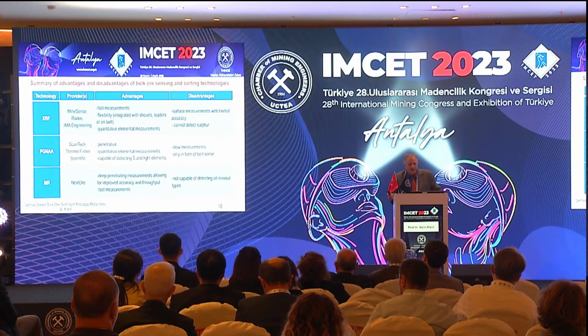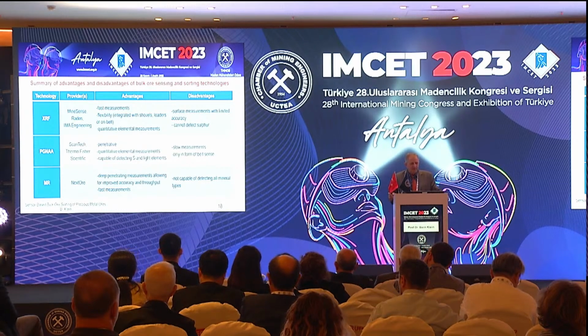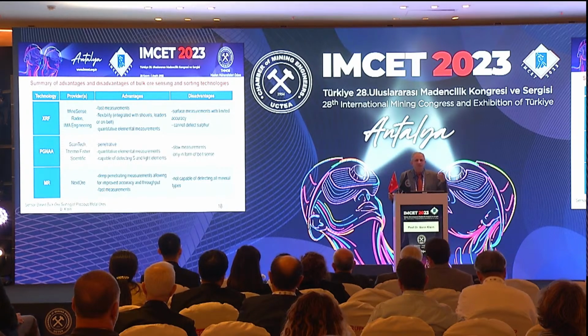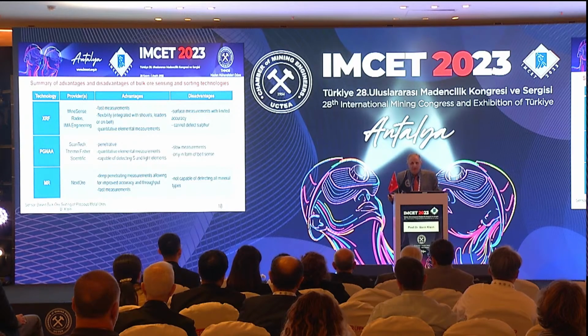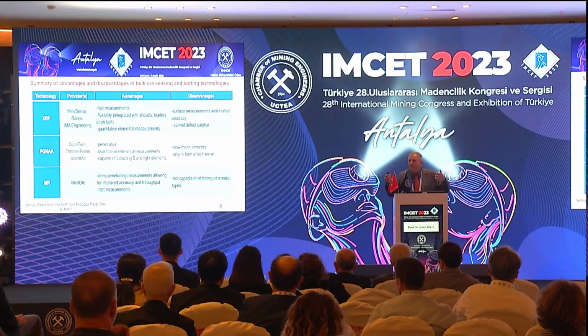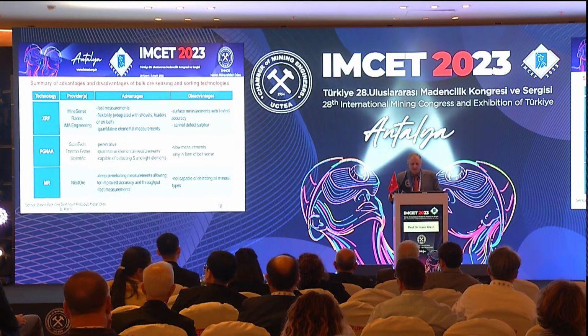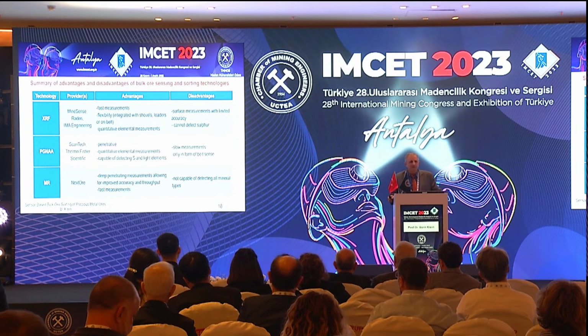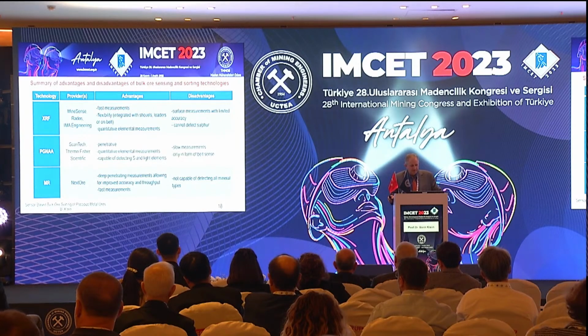The PGNAA can measure a lot more elements than XRF, including sulfur, and it's penetrative. It penetrates through the rock to give you a composition of not only what's on the surface, but what's on the inside of the rock. It can be a little bit slow, so that means that you may not have the sorting resolution. You may not be able to sort at 100-ton scales. It might be a few hundred or 1,000 tons. It's only on belts, so you've lost some heterogeneity by the time you've transported the material to belts.